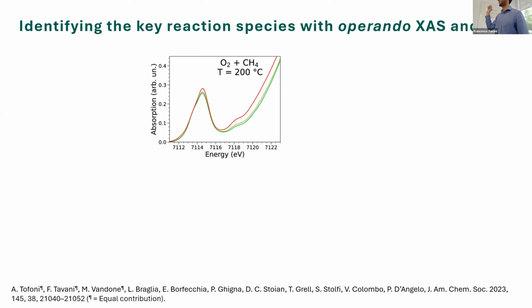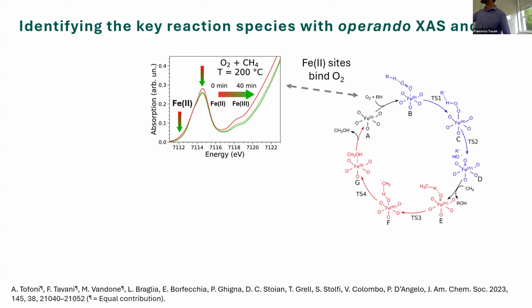Identifying the key reaction species. This was the aim. So these are the experimental data, and now we have the activated MOF. The corresponding spectrum is shown in red. And then we run the reaction in the presence of oxygen and methane at 200 degrees. And you see that there is a shift towards higher energies of the main absorption edge. This means iron 2 is going to iron 3. And at the same time, this very small shoulder decreases. This is due to the oxidation of iron 2 to iron 3. And this is all initiated, of course, by oxygen binding to the iron 2 sites.